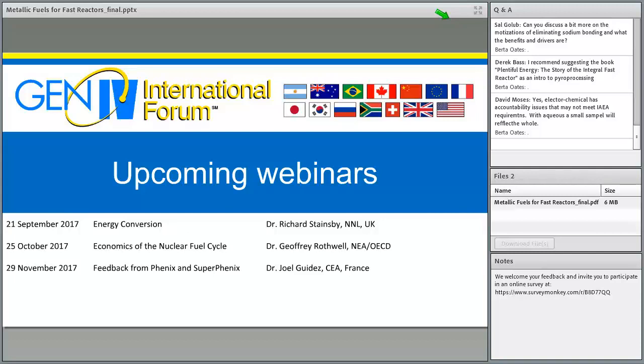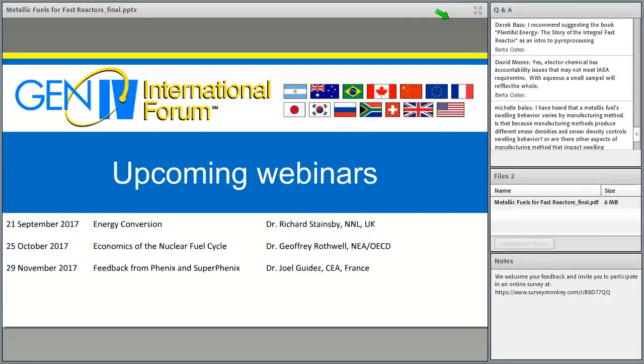Michelle Bales has the question: I've heard that metallic fuel swelling behavior varies by manufacturing method. Is that because manufacturing methods produce different smear density? So yes and no on what you've heard. Generally, metallic fuel behavior can be affected by fabrication method if that method introduces severe microstructural orientations, a pronounced texture. So for instance, extrusion or rolling of metallic fuels, which can create a highly textured metallic fuel microstructure, that can change some of the swelling characteristics.